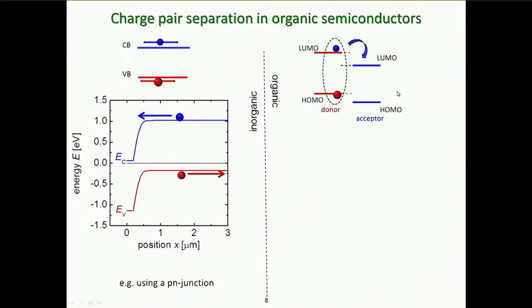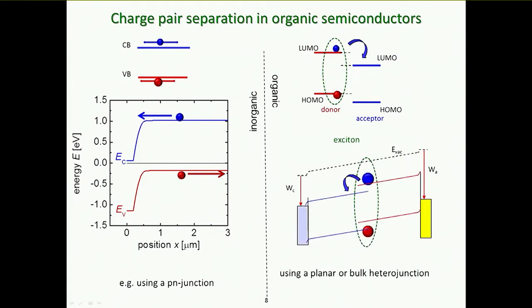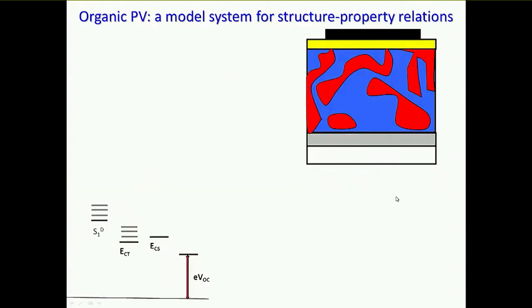We need first to liberate the charges, and that's typically done by using this device of a heterojunction, where a second material with a higher electron affinity attracts the electron away from the exciton. And then, having done that, this heterojunction can be embedded in a device where you have electronically different electrodes, not now created by doping, but by using different work function metals, and that then provides the direction that we need for a photocurrent.